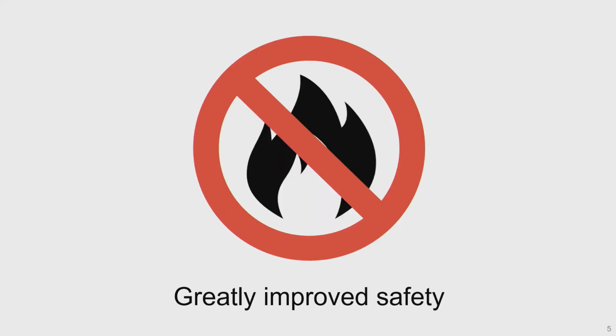And the other key factor we think really is the safety profile of the chemistry. For lithium ion, safety already for these high energy batteries is somewhat questionable. But you can kind of engineer your way around that with proper systems. With lithium metal, this is even a greater challenge because lithium metal inherently is a less stable system. So you really need to get around that by having a fundamentally very safe chemical system that prevents battery fires and other reliability challenges with high energy batteries.